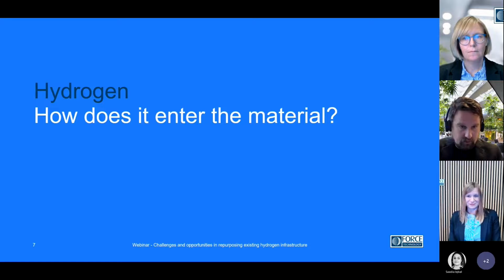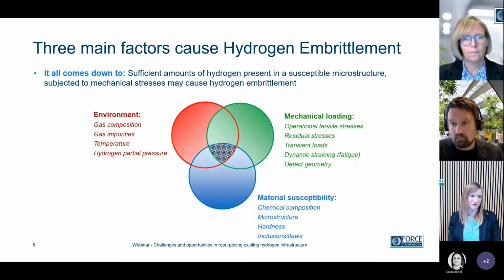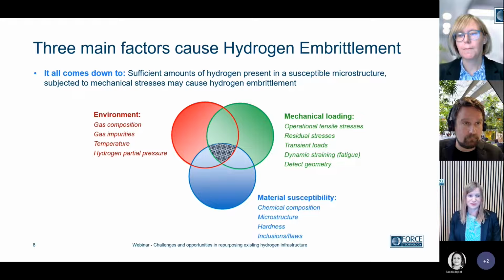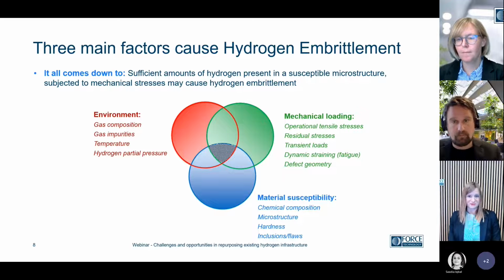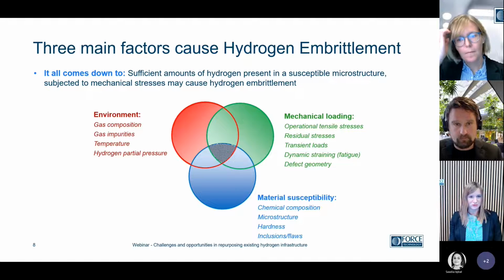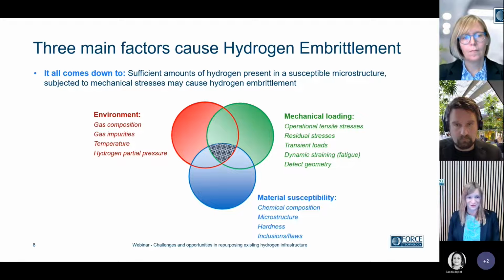But hydrogen, does it even enter the material? Blending or not, it all comes down to sufficient amounts of hydrogen present in a susceptible microstructure and mechanical stresses. And in the end, this may cause hydrogen embrittlement. This is something we can use actively when assessing materials for hydrogen. We cannot put a specific limit on each of these circles, but in the center, this is where hydrogen embrittlement occurs. So if we have a very low mechanical stress level, the green circle, we can allow more hydrogen and a more susceptible material, the red and the blue circles, and still avoid hydrogen embrittlement. If we have a very susceptible material, and we're not able to handle the hydrogen environment because it is 100%, then mechanical loading is a handle to turn on.